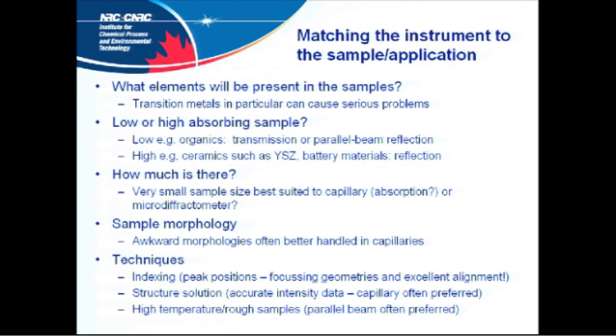In many instances, you find that a single experiment is not sufficient for all the techniques you're going to be using. In some instances, you may need to collect 2 or 3 different data sets, depending on the particular technique that you want to use. So in some instances, one data set for indexing for particularly good peak positions, and then extra ones for, say, the structure solution or refinement or anything else.